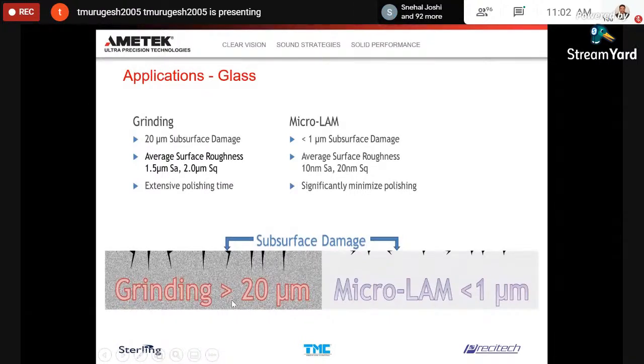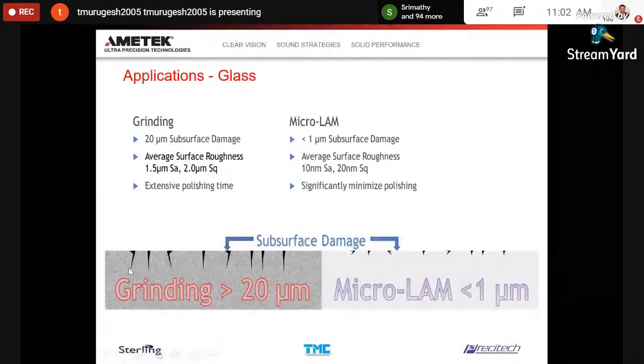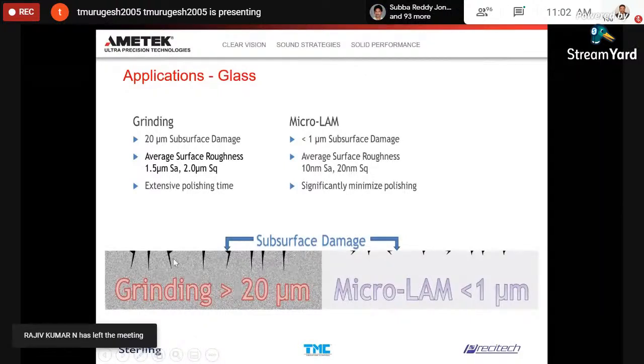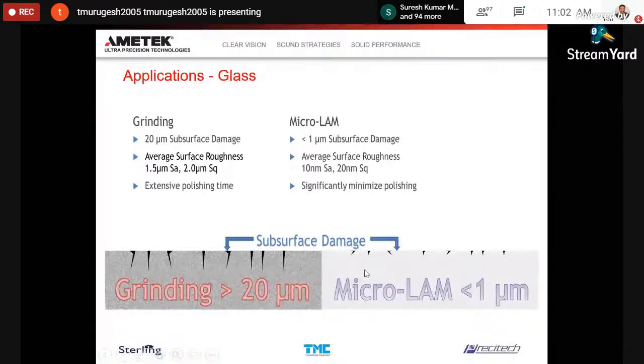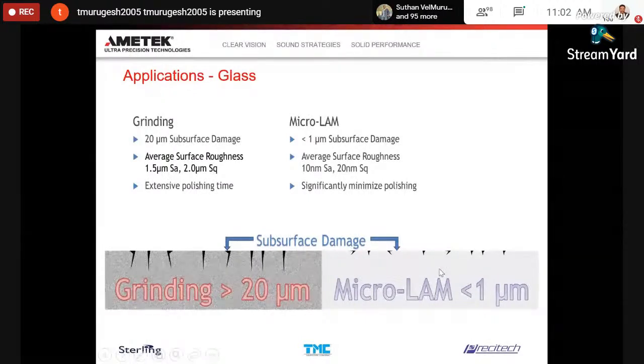And in a grinding application, the subsurface damage would be more than 20 microns. And when you want to make an optic, for example, a lens or any feature, these need to be polished or ground to this level to remove the subsurface damage. It takes a lot of time, maybe days together, to remove this material. So with the microlam, if you look here, the surface damage created on a glass surface is less than a micron. So it becomes simpler, and significantly reduces or minimizes the polishing time or the preforming time.